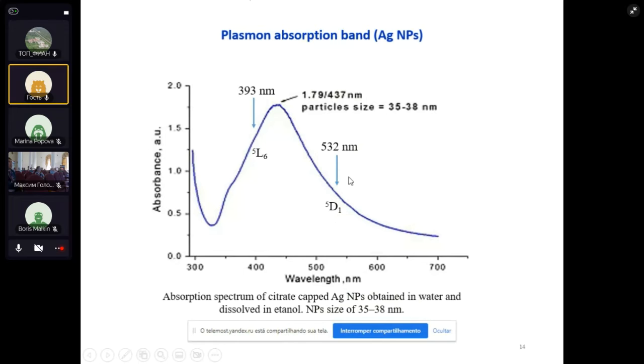a completely different result. And we would indeed expect this, because if we excite here, energy transfer to the plasmon band should be much more efficient than energy transfer from the quintet D1 to the plasmon band, since it is above the maximum. It is still inside the band. It's a very broad band, but the quintet D1 is far from the peak of the plasmon band, but it is still inside the band. So this is an important aspect.